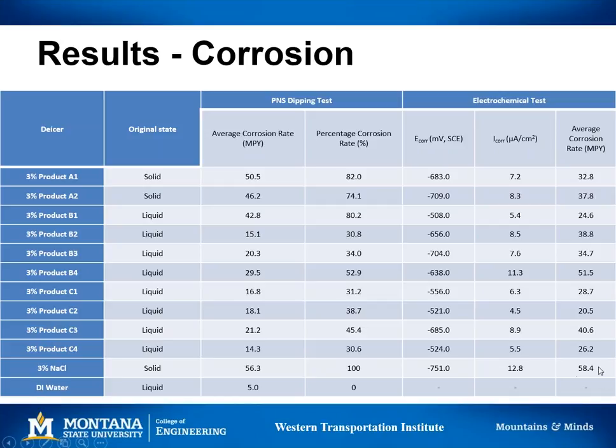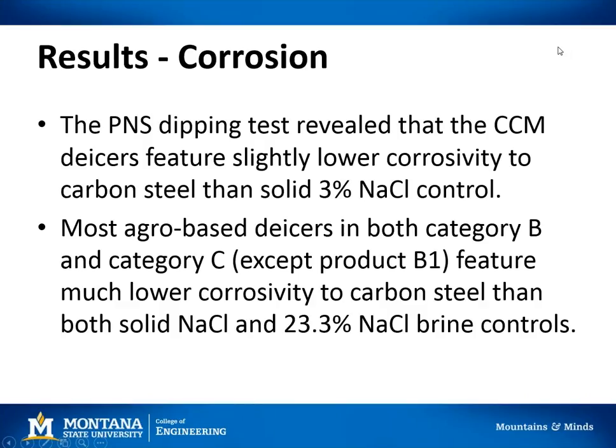So here's the salt brine control, and you can see here that all the products, with the exception of a few, they're a little high, have much lower corrosion scores. So in general, the PNS dip test, which was that test where you dip those 3 washers in, revealed that the complex chloride mineral deicers do have a slightly lower corrosion score than the salt brine control. And most agro-based deicers in category B and category C have much lower corrosion to carbon steel than the sodium chloride controls, with the exception of one product, and that just may need to be retested.